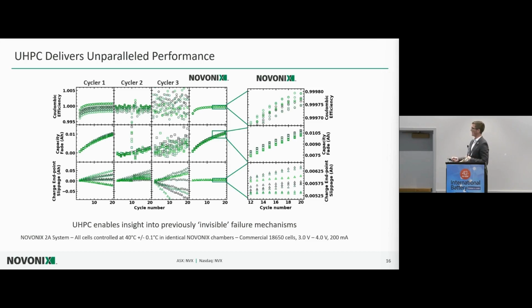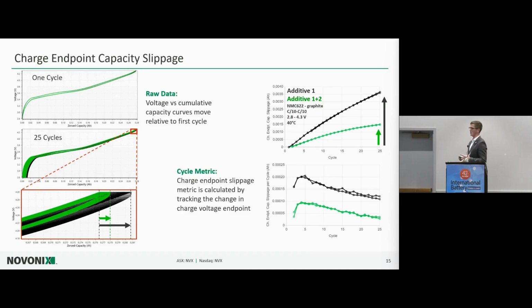With capacity fade, we also see generally this trend, even if you're kind of going up and down cycle to cycle, you get your general trend. This is a cumulative effect. So, you can do capacity-based measurements and look at fade on any type of equipment. And really what makes things stand out is this metric called charge endpoint capacity slippage, which I'll describe quickly in this slide. And this is how we start to quantify some of these slippage-based mechanisms.